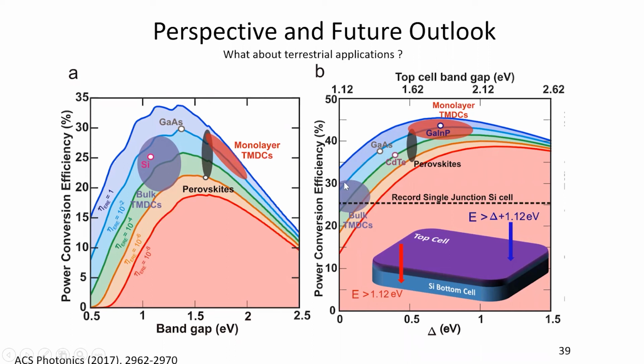So they're only going to give you modest improvement if you combine them on top of silicon. But monolayer TMDCs are actually very well matched in terms of band gap. And the fact that 2D materials can be layered on top of anything, as opposed to III-Vs, which are difficult to grow epitaxially and in high quality over arbitrary substrates, means you may have some opportunity in terms of integrating TMDCs in tandem cells on top of silicon.